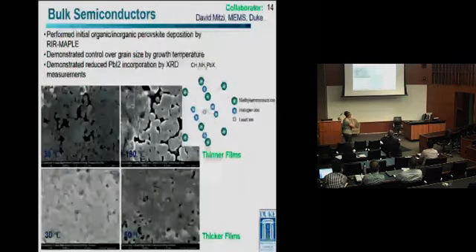Another example David Mitzi spoke about earlier today, again, looking at the perovskites. So it talks about how perovskites are very exciting for solar cells because they've gotten such high efficiencies in a relatively short amount of time. But one thing that's unique about them is that they are a hybrid material, with organic and inorganic components. And a challenge can be, especially if you want to start playing around with what this recipe is, how to find a solvent that's compatible with both components. But we eliminate that need by MAPLE.